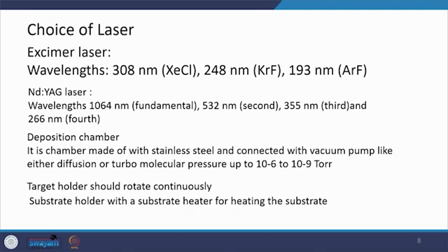and 193 if you use argon fluoride. Similarly, the fundamental wavelength for the Nd:YAG laser is 1064 nanometer. Generally we do not use this. The 532 nanometer, in the visible range, is also not very useful, but more useful are 355 nanometer and 266 nanometers.